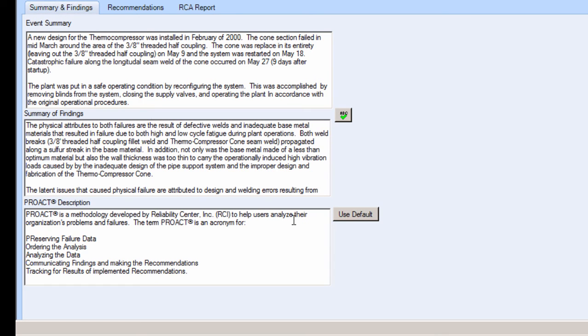The physical attributes of both failures are the result of defective welds and inadequate base metal materials that resulted in failure due to both high and low cycle fatigue during plant operations. Both weld breaks, the 3/8 inch threaded half coupling fillet weld and the thermo-compressor cone seam weld, propagated along the sulfur streak in the base material. In addition, not only was the base metal made of less than optimum material, but also the wall thickness was too thin to carry the operationally induced high vibration loads caused by inadequate design of the pipe support system and improper fabrication of the thermo-compressor cone.